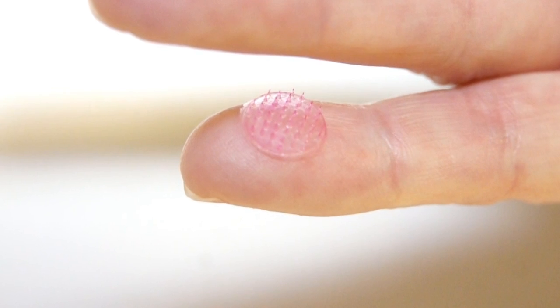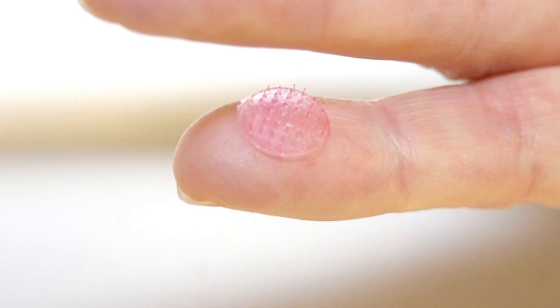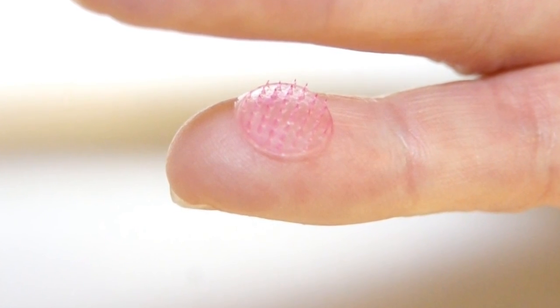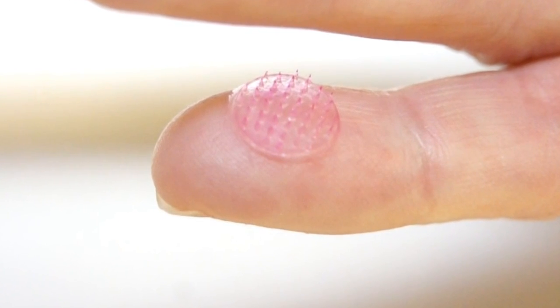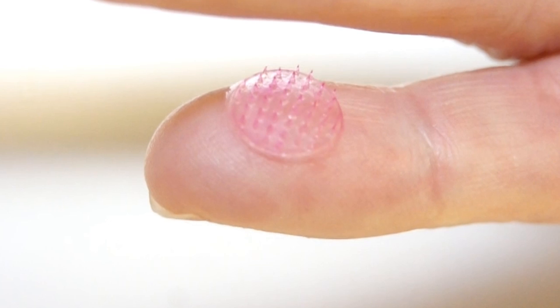We then flip out these little discs which have little sugar spikes, and administer what we call microneedle arrays to the skin of mice to address whether we can stimulate a potent immune response. The sugar needles are very sharp and that's sufficient for the vaccine to be able to penetrate the skin; they dissolve very quickly and then release the vaccine that's in the spike.